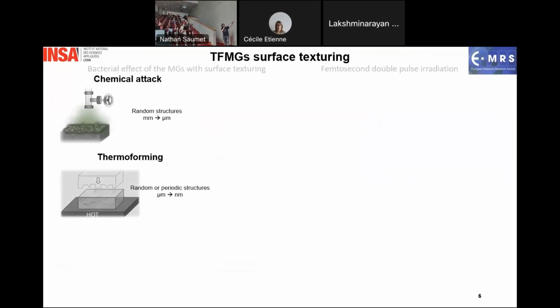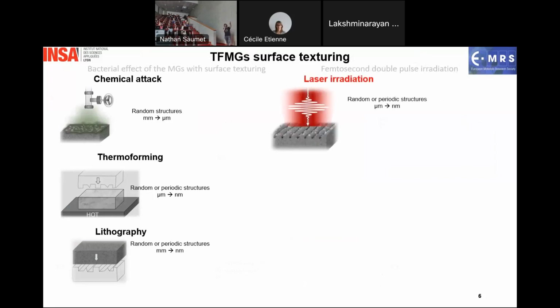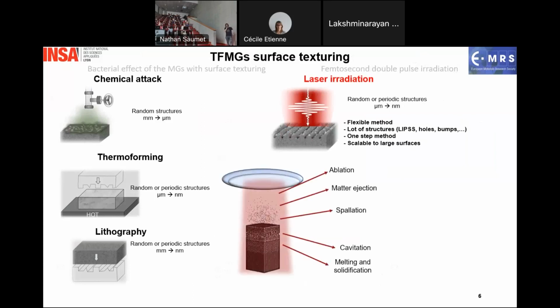We have a lot of possibilities to structure the surface, like chemical attacks, thermoforming, or lithography. But in this project, we want to use a laser irradiation process, which permits structures from the micrometer to the nanometer at large scale. The advantage is that it is a very flexible method, and we can obtain a lot of structures just by changing some parameters, structures like LIPSS, LSFL, HSFL, holes, bumps, spikes, etc. And it's also a one-step method. Just the irradiation process, and we have a texturing of the surface.